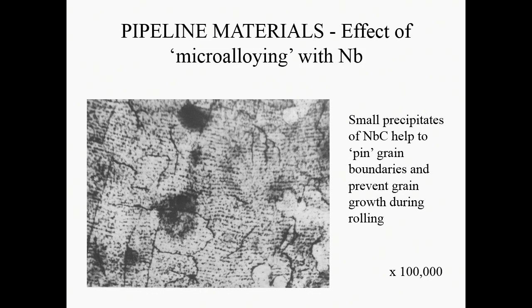If you go too high in temperature, the grains will grow because niobium carbide will dissolve. So this really only occurs at the bottom end of the rolling range, i.e. in the cold rolling range. So we stop grain growth from taking place by these carbides, and that also allows us to get grades above X80, so X100 and things like that.